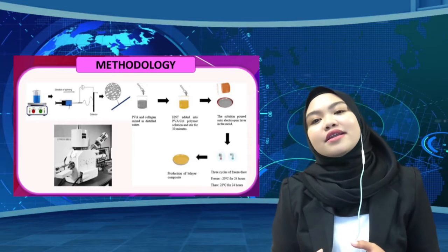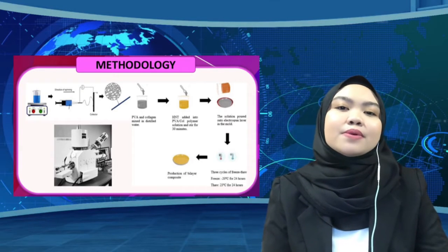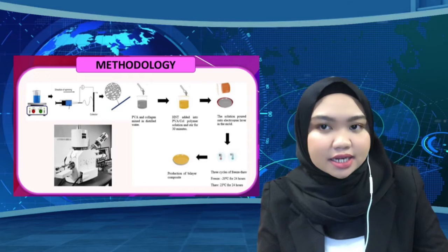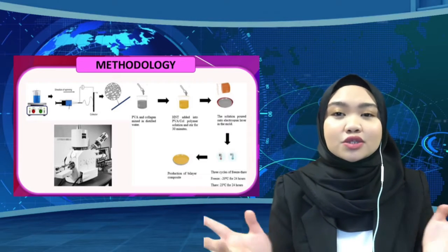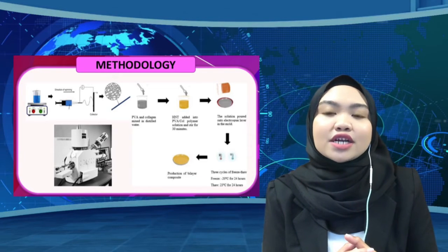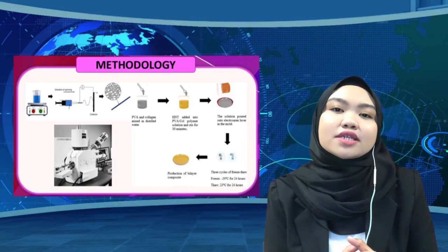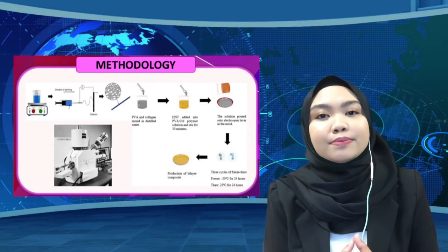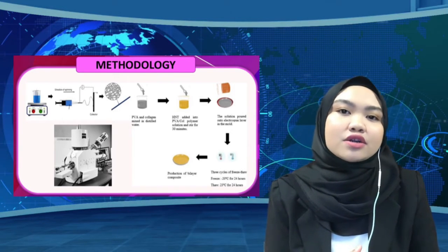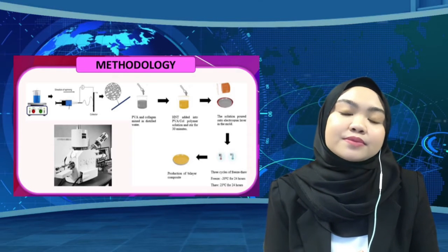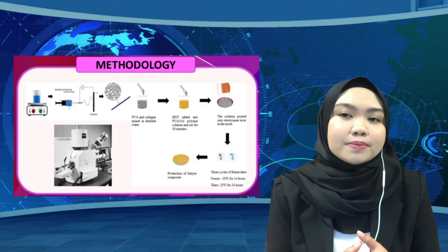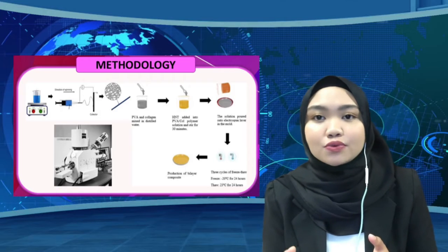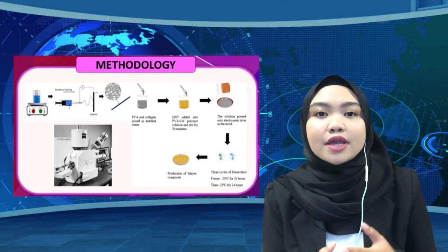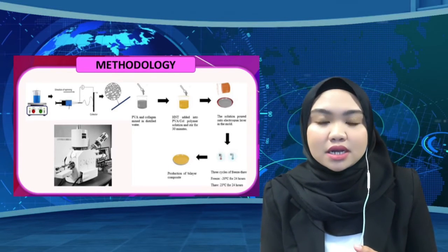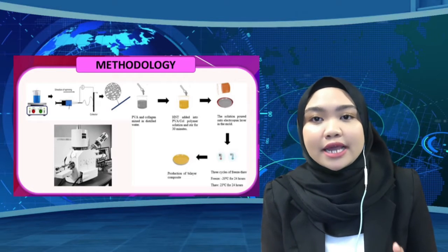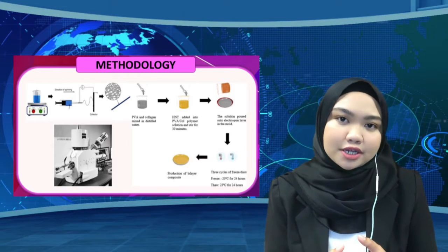Tensile strength and Young modulus for film samples were obtained with a tester at room temperature, 22 Celsius, using a 5.6 Newton load cell, 21 mm per min preload stress speed and extension rate of 10 mm per min. Samples of different composites were cut into rectangular shapes with a gauge length of 50 mm and width of 10 mm. The samples were clamped and subjected to tension until breakage.